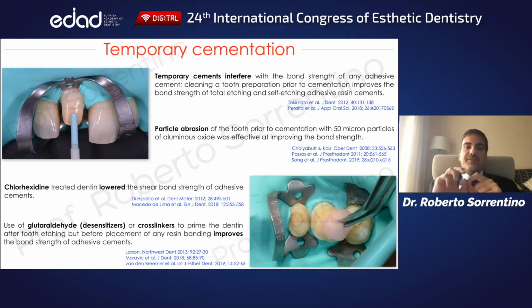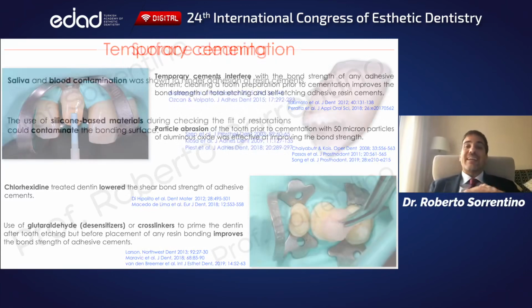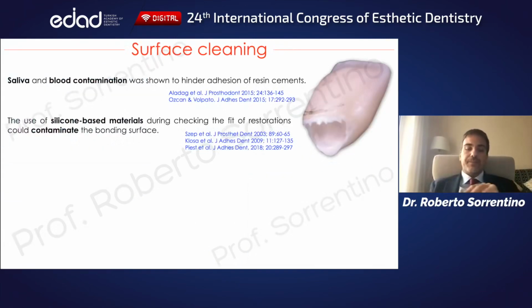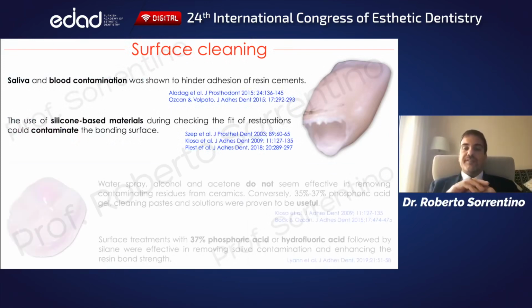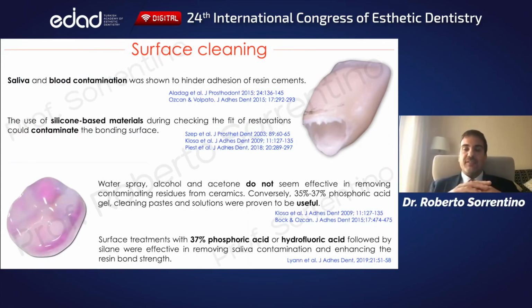Substrate surfaces have to be cleaned before the final cementation, and not only blood and saliva should be considered contaminants, but also silicone-based materials and any other particle debris. Water and acetone are not useful to remove the remnants, whereas the application of cleaning pastes and phosphoric acid proved to be effective in removing all the contaminating debris.